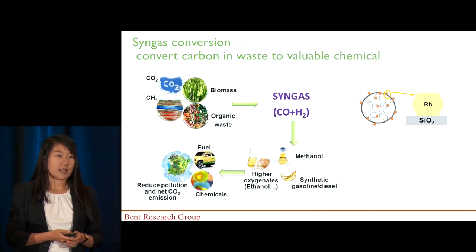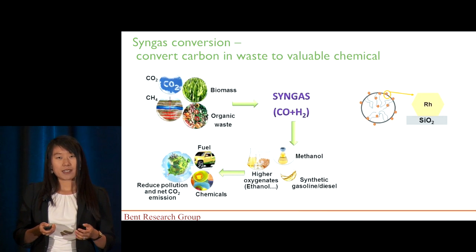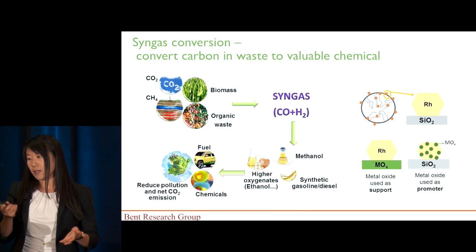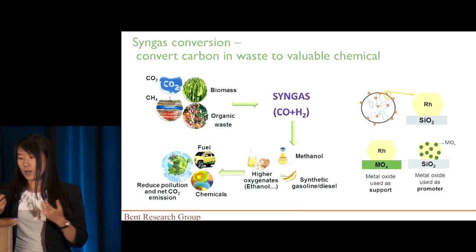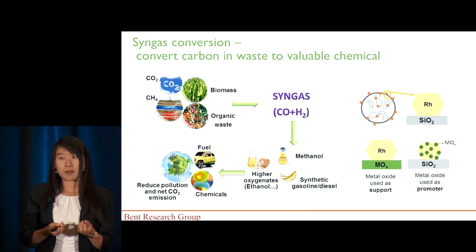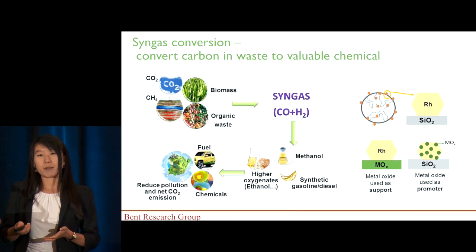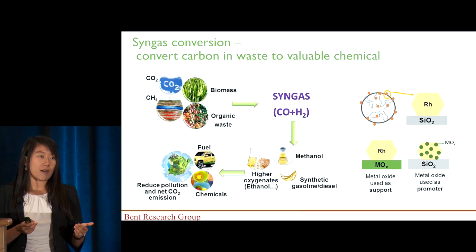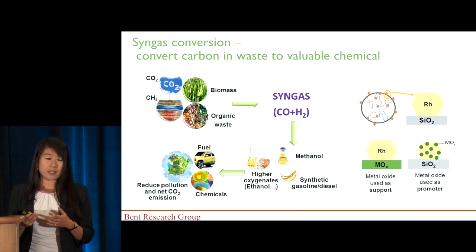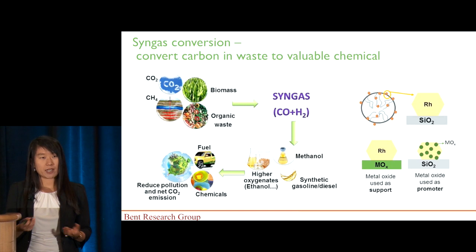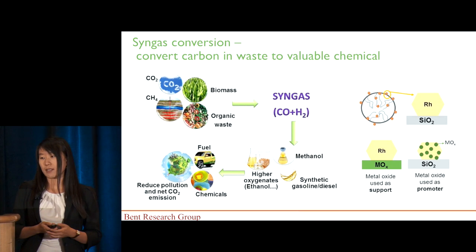Rhodium-based catalyst is one of the major candidates. One very interesting and important factor is that the support material or the promoters can actually largely determine the catalytic performance. In heterogeneous catalysis, promoter refers to a substance added into the catalyst to improve its activity, selectivity, or lifetime. For rhodium catalysts, by using different metal oxides as either the support material or the promoters, the activity and selectivity can be dramatically changed. Therefore, our research is focused on understanding how these metal oxide species influence the catalytic performance.